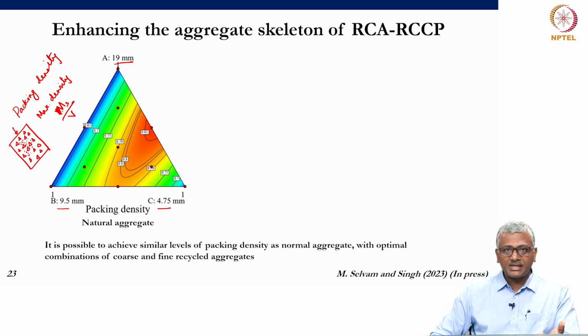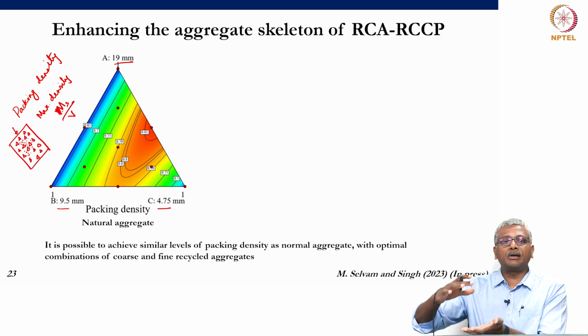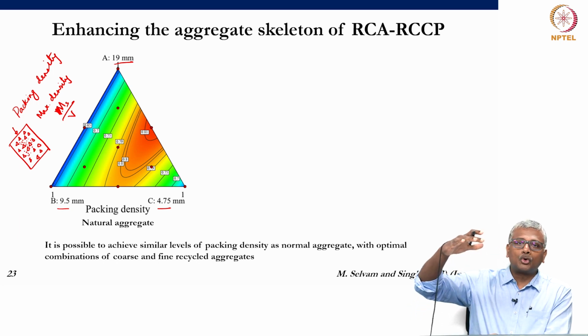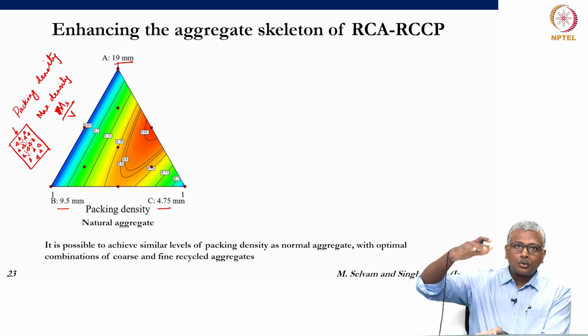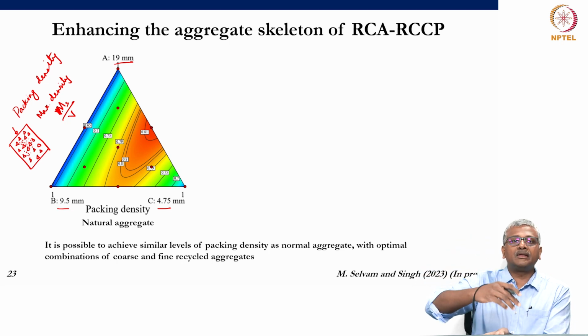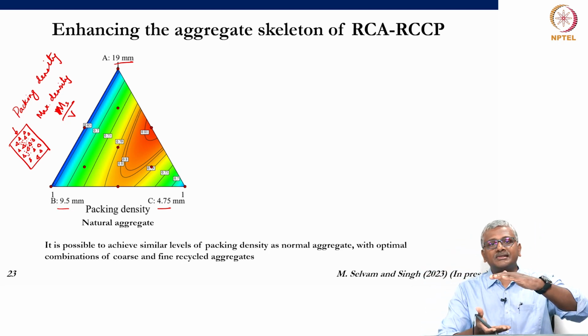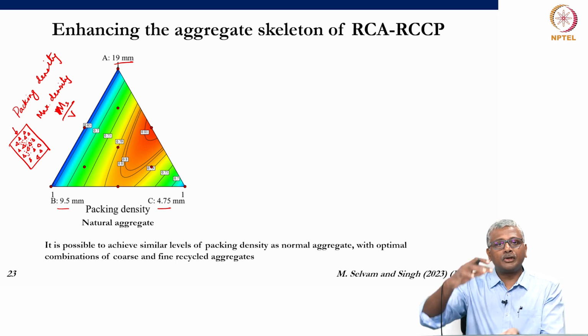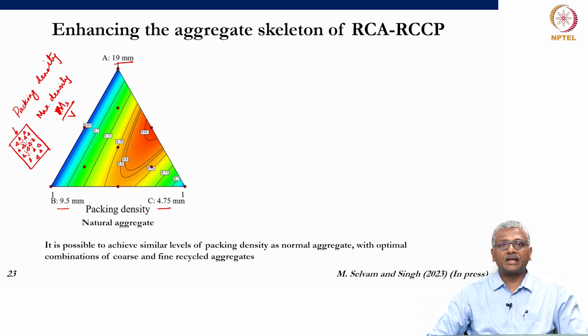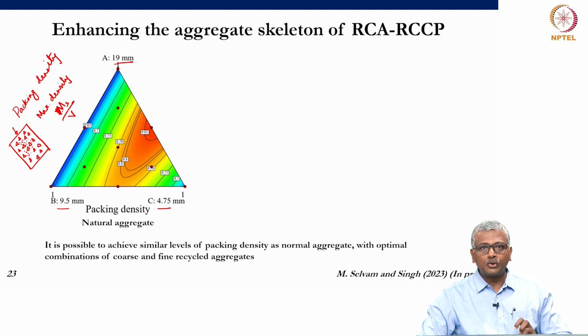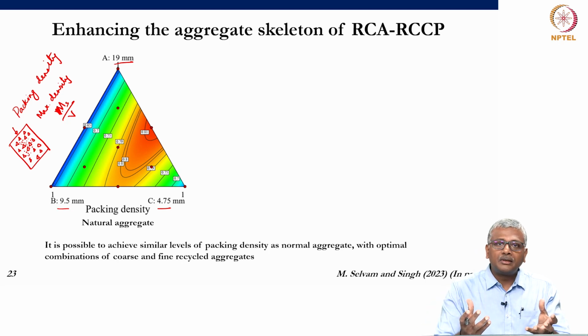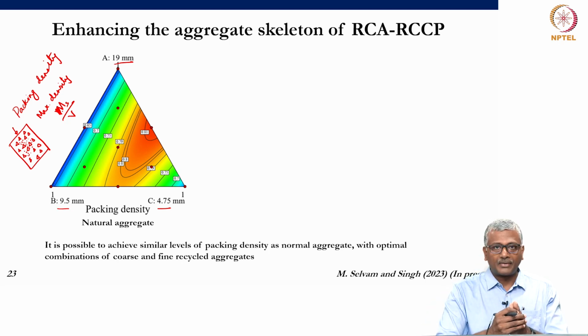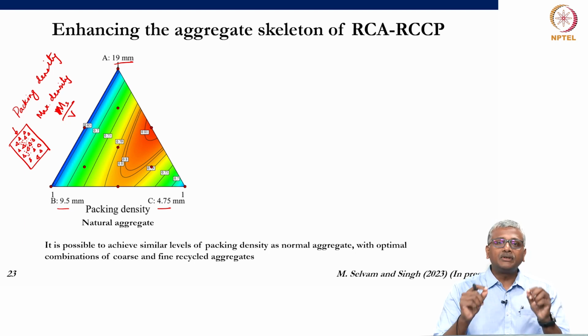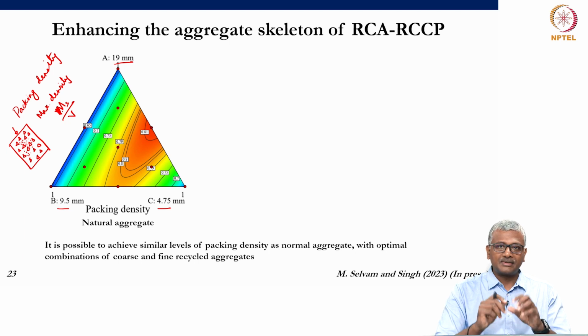Of course, when you do the same experiment with roller compacted concrete, you have to also simulate the fact that you are going to be using a roller to do the compaction. So, in such cases, you can't just measure the density by simply mixing and putting into the container, you also have to simulate the compaction action somehow. But what we are trying to do is maximizing the proportion of aggregate in the system, okay. So, maximizing the density of packing of the particulate inclusions in the system.